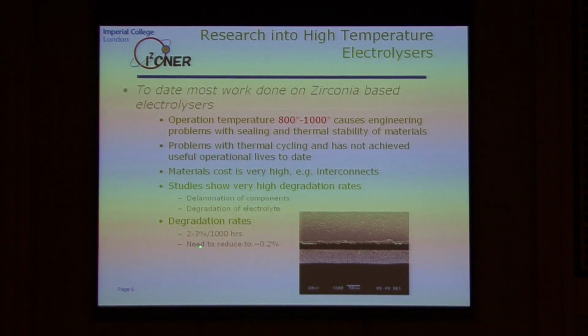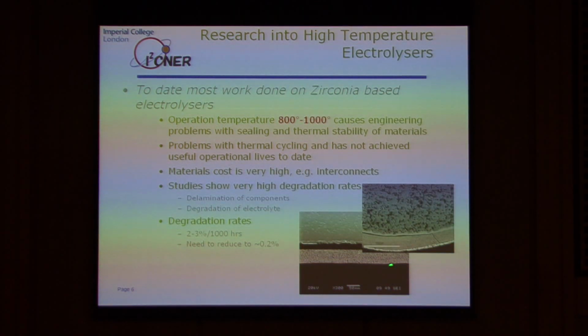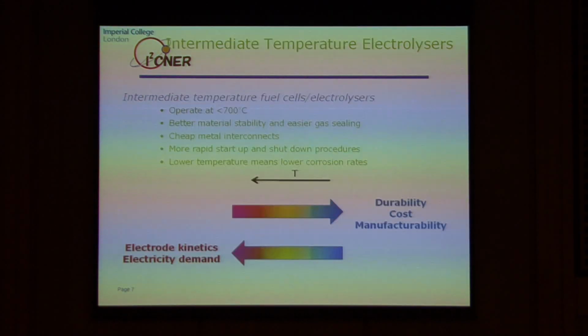To get into commercial operation, we need to get those degradation rates down, initially at least, by a factor of 10. One thing that happens is delamination of components. This is part of a cell - here's the electrolyte, and here's the cathode - and by the evolution of oxygen, we've almost blown the cathode away from the electrolyte. Here's a cell we were working on with colleagues at Imperial College, a tubular cell, where at high current densities we created so much gas that we delaminated the system.